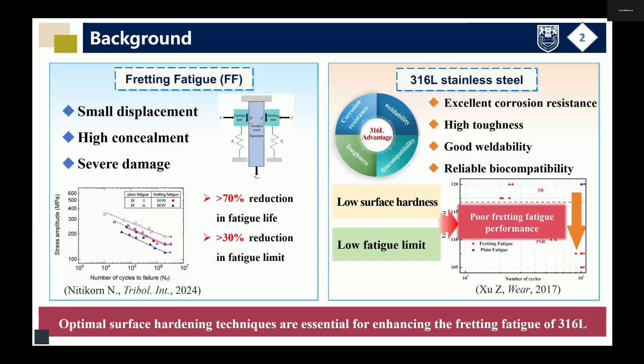Fretting fatigue, as a typical form of fretting damage, is characterized by very small relative displacements, high concealment, and yet extremely severe consequences once cracks initiate. Fretting can shorten the fatigue life by more than 70% at the same stress level and reduce the fatigue limit by over 30%.